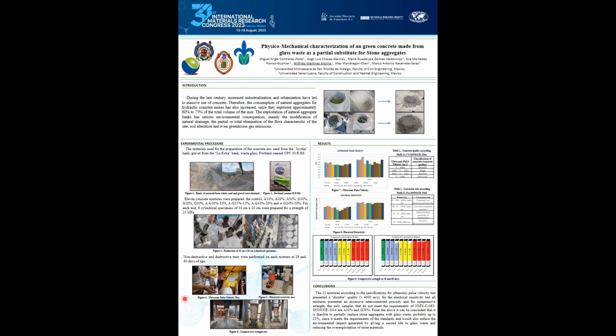As conclusions, we can say that all 11 mixtures comply with the specification for ultrasonic pulse velocity, presenting a durable quality. For the electrical resistivity, all the mixtures present excessive interconnected porosity, and for the compressive strength, the only ones that do not comply with the design strength were the A30% and G30% mixes.